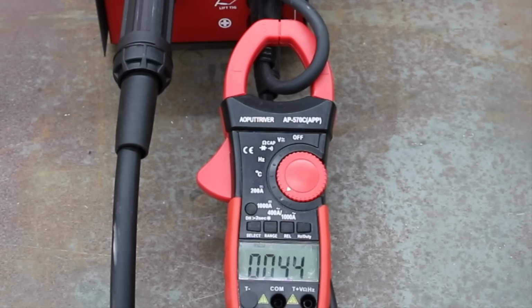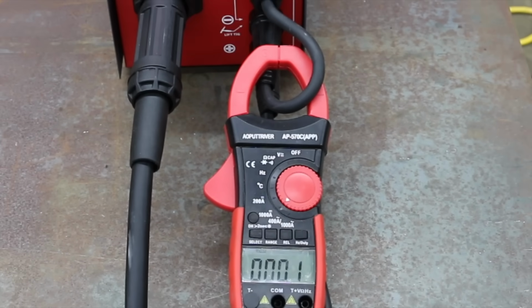On the lowest heat setting, there's quite a bit of fluctuation from 41 to 106 amps. And the welding started off at 229 amps and dropped to 211 after 3 seconds.